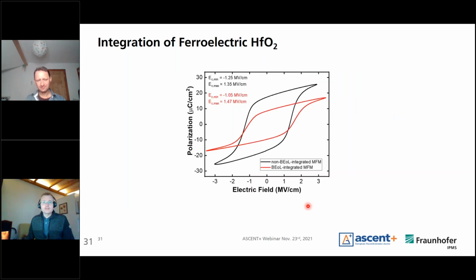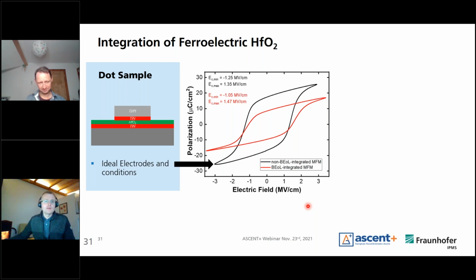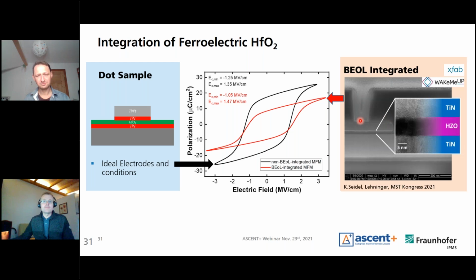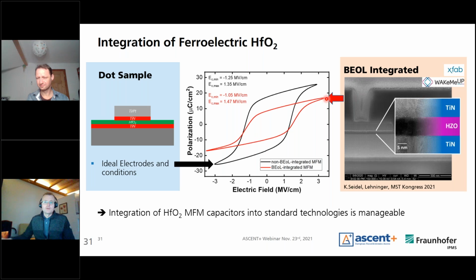Okay, and this is just an example from a project that we've done in the past years together with X-FAB. We first of all optimized material based on dot samples, so we got very high 2PR values, which are quite well. But of course, in real back-end of line conditions and also using existing technologies, it is getting a bit lower, but still we can achieve low leakage and considerable switching behavior of the ferroelectric material. So that shows that it is manageable, and of course there's further room for improvement, but in general the implementation is not a high problem.